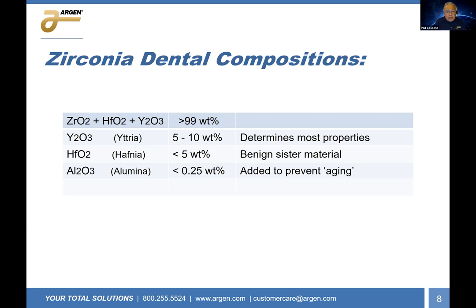The alumina content is, as I listed here, less than 0.25%. You may remember the first zirconia, the zirconia material, was very opaque. It was very chalky white. And this is the reason why. The alumina in there was like 0.25%. And it was there to prevent something that happens with zirconia, and that's called aging. Water can get in between the particles, the grains, which I'm going to show you in a minute. Water can get in between the grains and actually disintegrate the material. The material just falls apart. It was a problem with zirconia that was recognized in the orthopedic application. The solution was to add alumina. The alumina sits in the grain boundaries and acts as a little cork. The water can't transfer into the grain boundaries, and therefore you prevent this aging reaction.